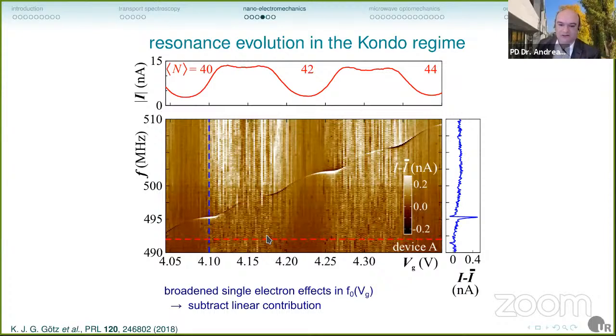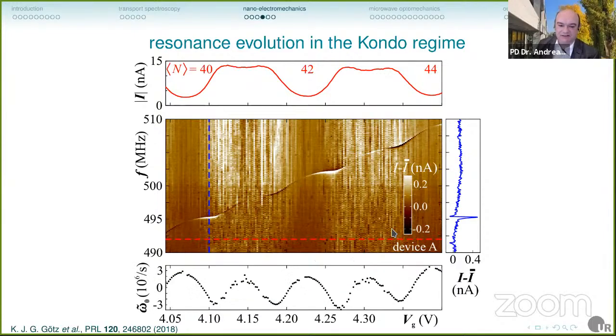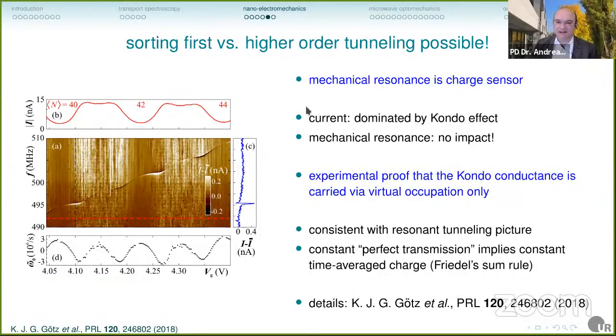And now we can look at how the mechanical resonance evolves there. And we can extract the resonance positions, we can extract the resonance frequencies. And as you can see, there is already an obvious difference between the upper and the lower curve. The upper one has this odd-even imbalance. So you get a Kondo effect for odd electron number, you get a Coulomb blockade for even electrons. But down here in the resonance frequency evolution, there is no such odd-even effect. And it turns out the mechanical resonance is acting here as a charge sensor and provides a quite nice experimental proof that the Kondo conductance is carried only via virtual occupation of your system.